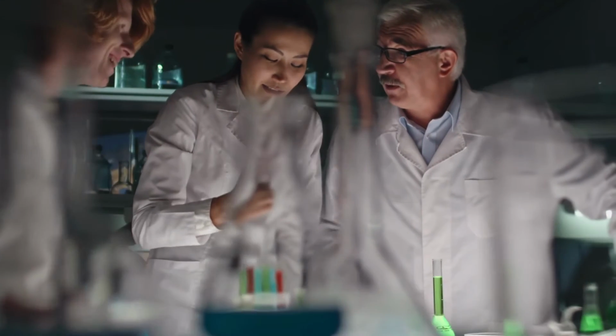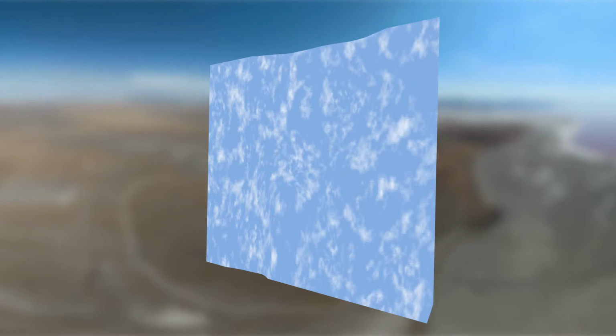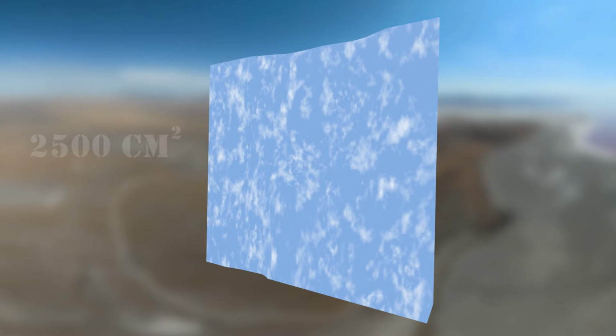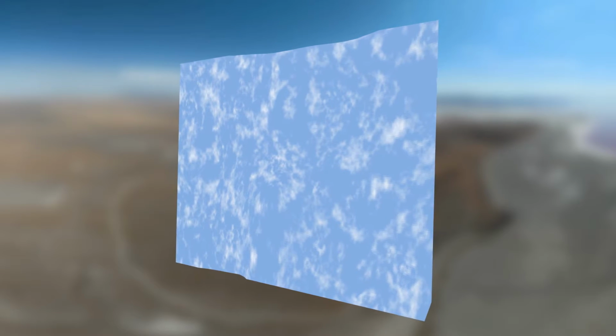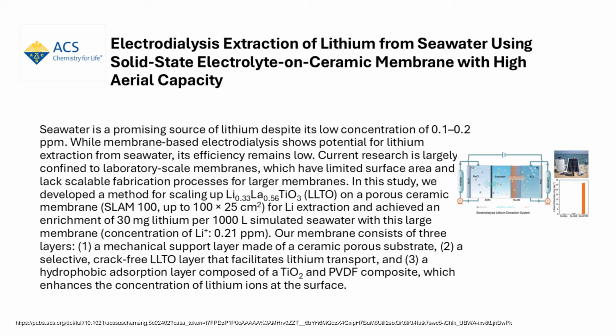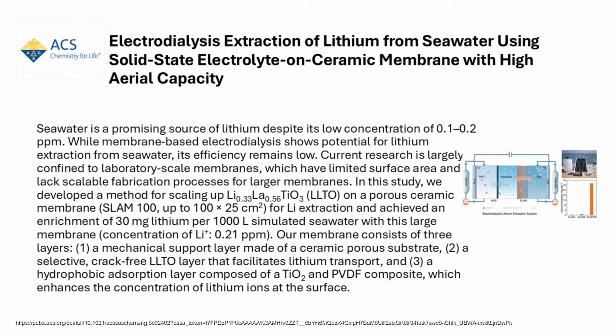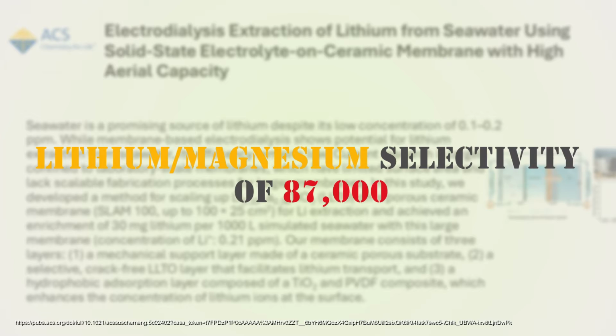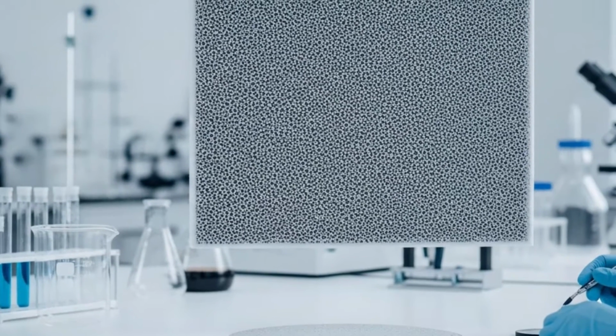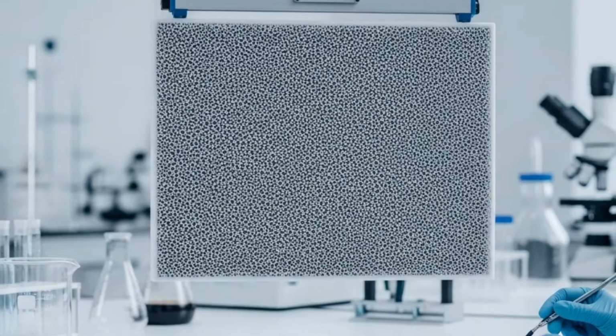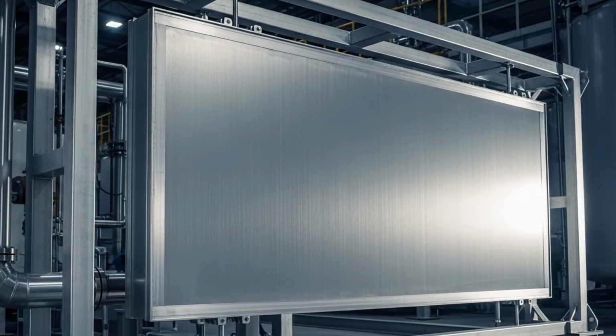This design allowed researchers to finally build large-area membranes, a 2,500 centimeter squared sheet, that maintained high performance. This large-scale membrane successfully extracted over 30 milligrams of lithium from 1,000 liters of simulated seawater in a single day, achieving an exceptional lithium-magnesium selectivity of 87,000. We are moving from small lab discs to industrial-sized filter sheets.